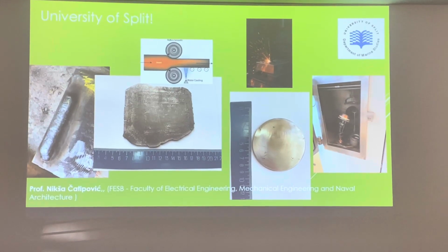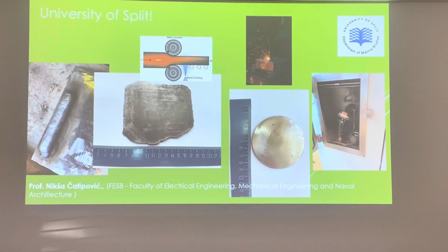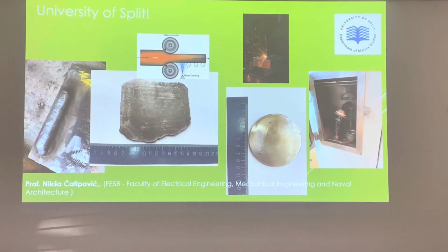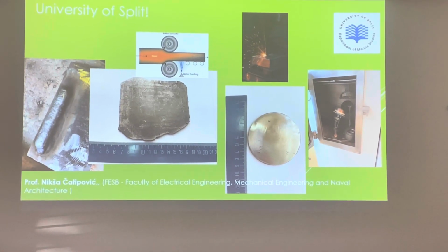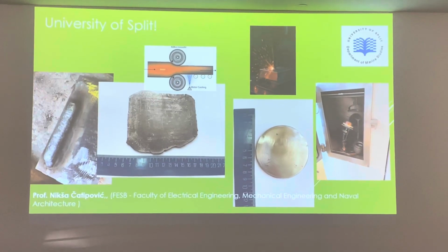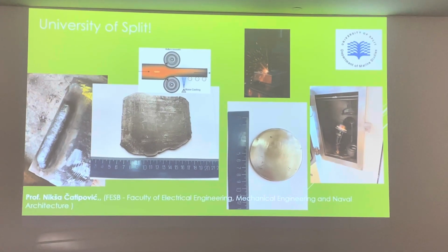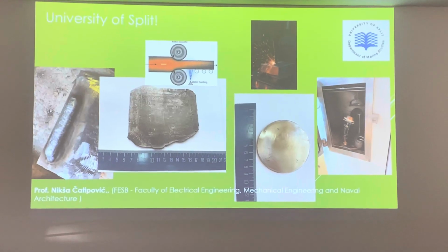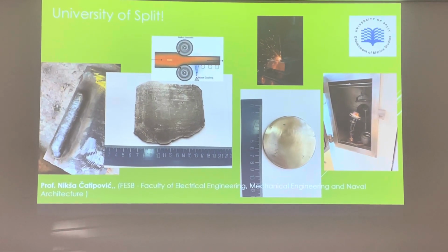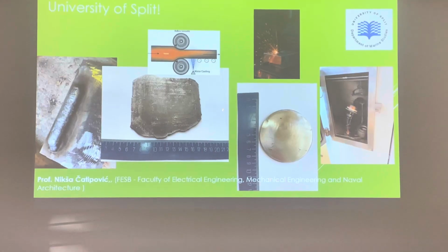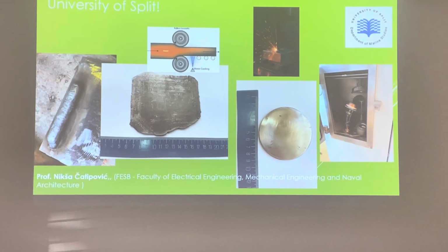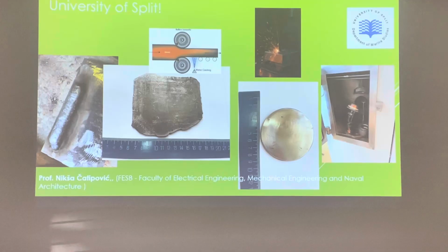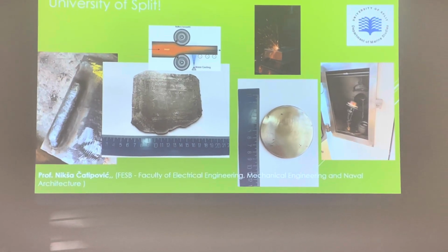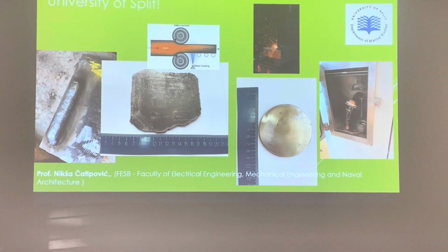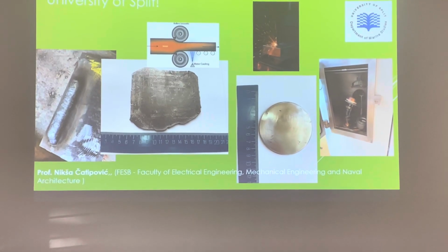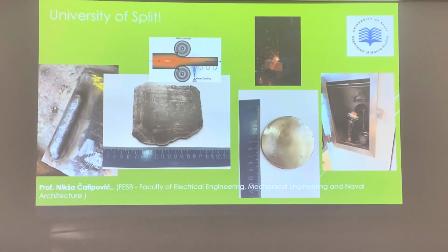Another application: we have collaboration with Split University, with Professor Nikša Čatipović, and we have made the following routine. We have printed a bulk sample. After that, we perform hot rolling and obtain a flat plate cut from that target for sputtering in magnetron sputtering. And also we have made some experiments and research with the hot rolled material.